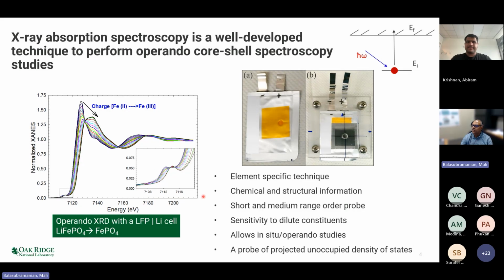Lastly, you can measure extremely dilute constituents with X-ray absorption spectroscopy. So you can measure things of the order of tens of parts per million if required. And so it's a probe which can give you a lot of information about dopants, which are now quite present in many of the battery materials.